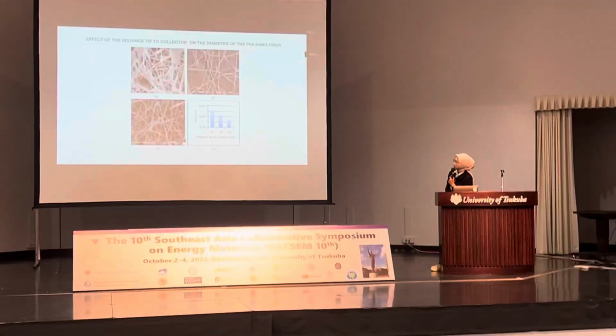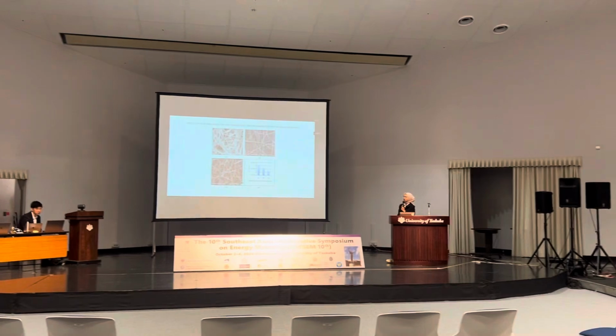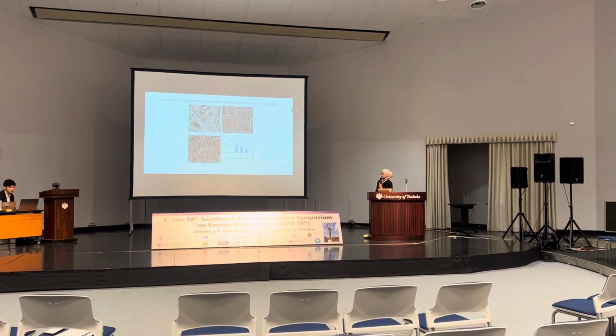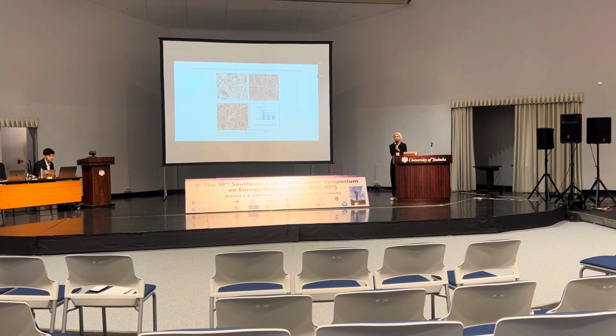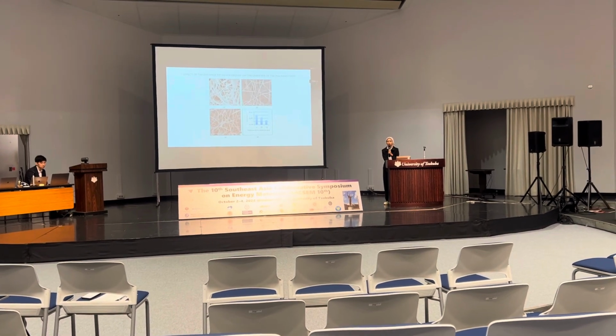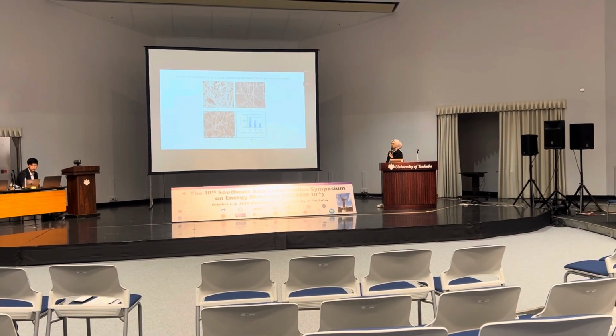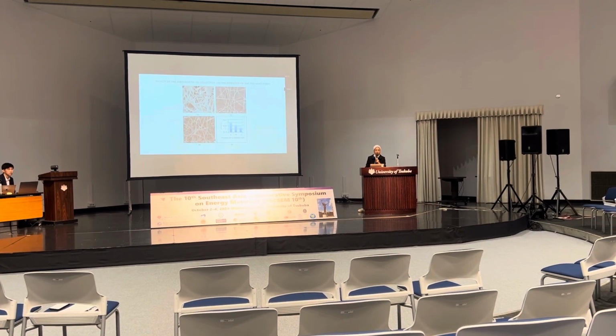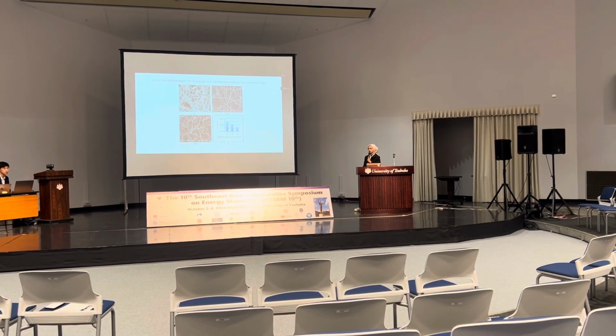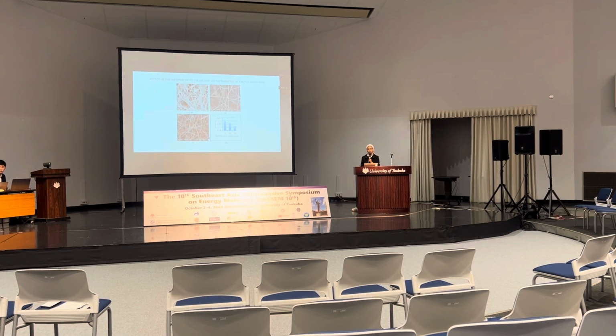Four, when the distance between the tip of the needle and the collector increases, the diameter is smaller, maybe due to the time required to reach the collector being longer. Therefore, the fiber will be more stretched.